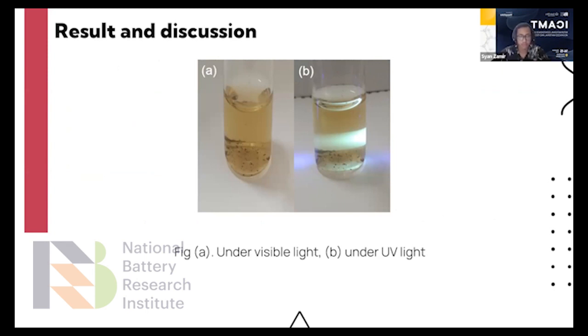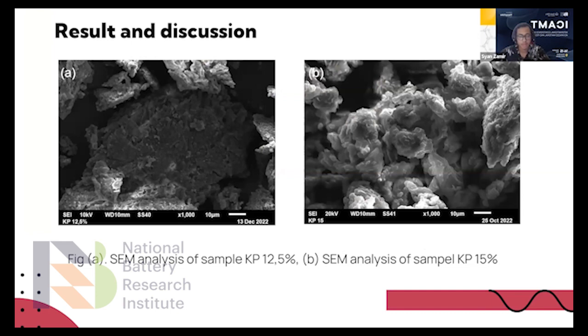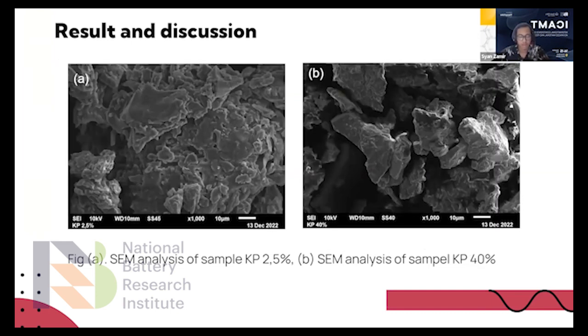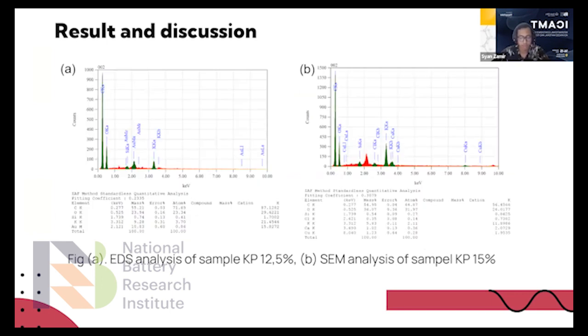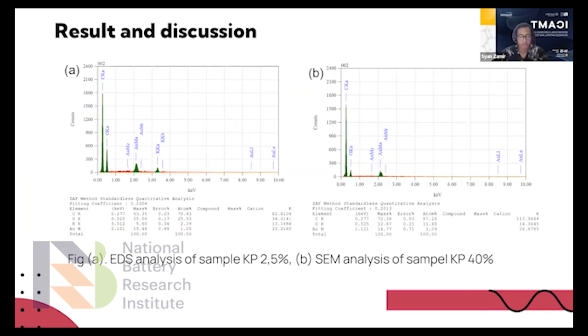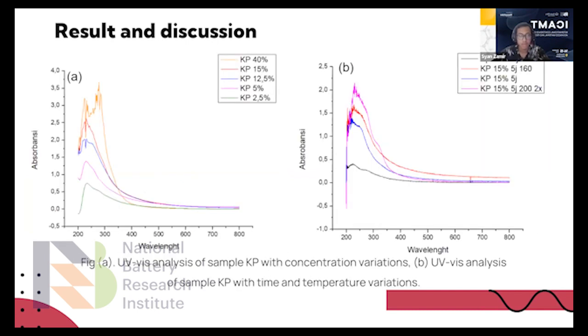Figure A shows solutions under visible light, and figure B shows the solution under UV light. This is an SEM analysis of the sample, and this is the EDS scan for each sample. It shows that more than 50% of the component is dominated by carbon when analyzed at E equal to 0.277 kiloelectron volt.